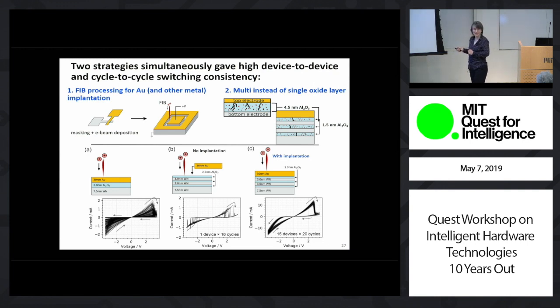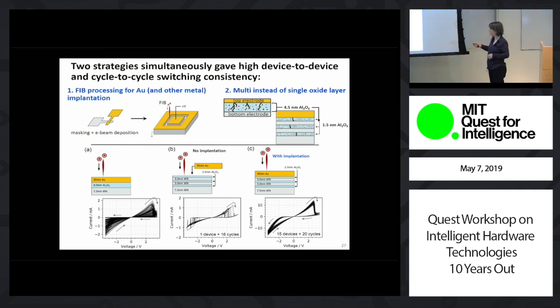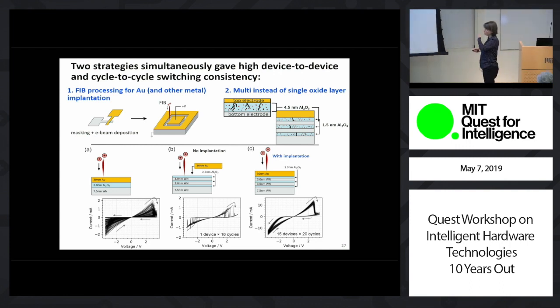So maybe a year ago, Zhengji came to me with this data: as I divide the number of layers, it improves the process, but I must put the gold layer and FIB mill it. Without FIB milling, it doesn't improve. That you get really good consistency. So what's happening here? Right? That's quite intriguing, and this result is really promising. So it's across more than 10 devices, 20 cycles in each, and I will show later cumulative distribution functions that it's a really tight distribution.